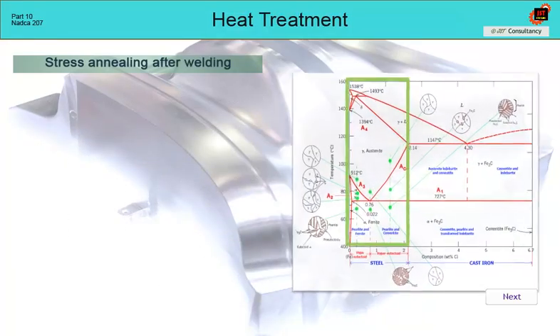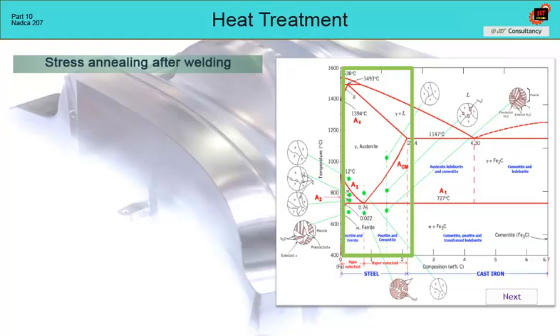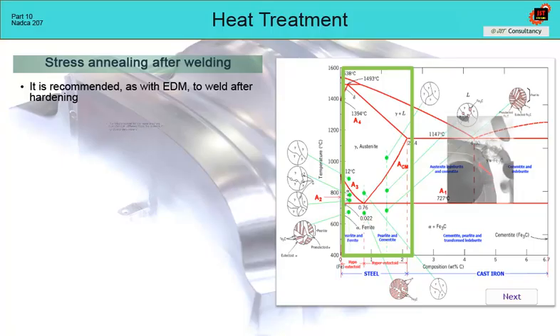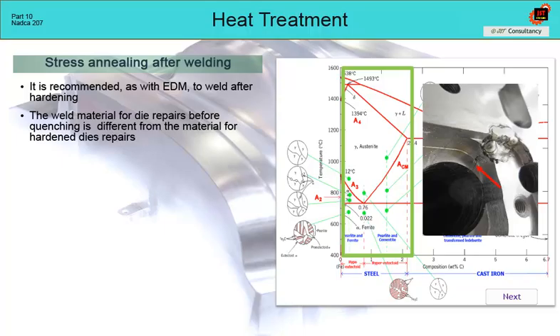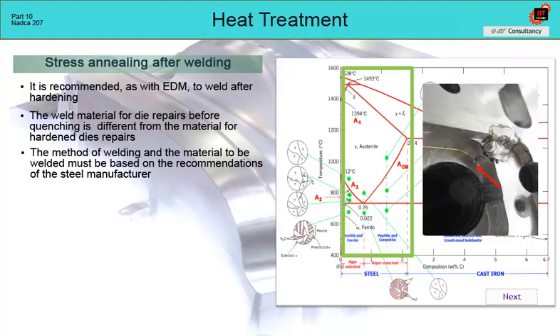Annealing after welding is another of the mandatory thermal processes. As with EDM, it is recommended to weld after hardening. In that case, the welded material has a chemical composition such that after welding and stress relieving, the same hardness as that of the insert itself is achieved. A maraging steel electrode is usually used. If welded before quenching, then the electrode has the same alloy elements as the die material, and will therefore exhibit identical quenching behavior. In all cases, however, it is necessary to always follow the recommendations of the steel manufacturer.